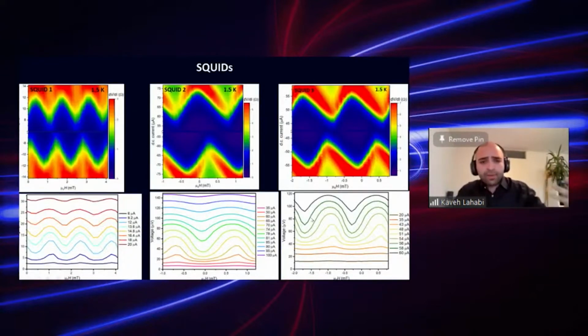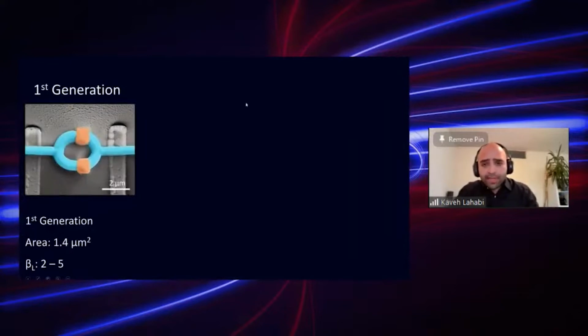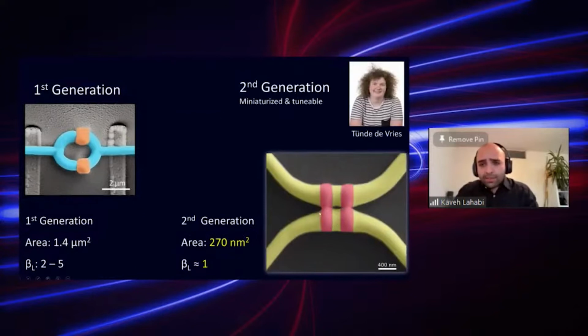But they were a little bit less reproducible, and there were some asymmetries in the junction. So we decided to actually change the design. So I'm now going to show you the second generation of these junctions. My student just managed to take the first SQUID with the new design, which is miniaturized and you don't need to apply a magnetic field. You could just use a passive current through one of these lines to tune your SQUID. And this of course substantially reduces the area of the SQUID and also improves the flux transfer function. But it's being measured as we speak. The bottom line is that we also managed to reduce the area by at least an order of magnitude.